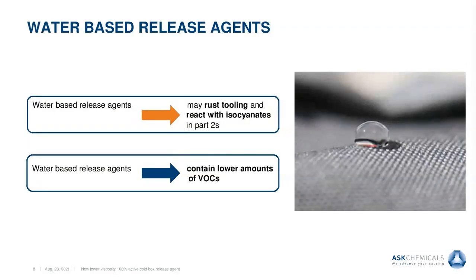Hence, the introduction of water-based release agents. They don't come without their fair share of disadvantages as well. The water may rust metal tooling. The water also reacts with the isocyanates in the cold box resin part 2s, which will lead to resin wipe-off. We don't recommend water-based release agents for cold box applications, although some customers are using them. Their biggest advantage, however, is that they typically contain lower amounts of VOCs compared to their solvent-based counterparts.